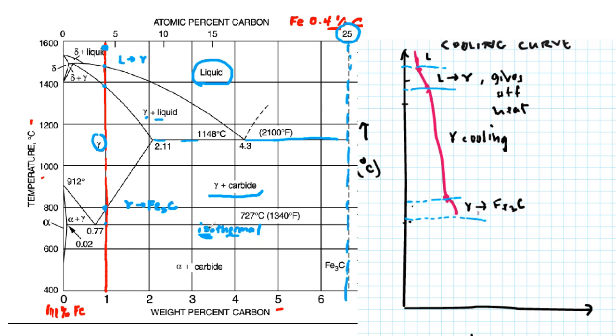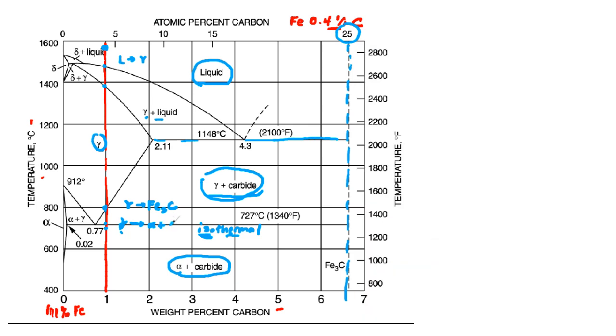So what we have is at this temperature we've cooled it down to this point, and what we have is a mixture according to this phase region label. We have a mixture of gamma and carbide. Now what happens when we get on the other side, you see that we are in a mixture of alpha plus carbide. Well that seems to suggest that all the gamma has converted into alpha and maybe carbide. So it turns out that is true, that at this temperature there is a reaction where gamma is converted to alpha plus Fe3C.